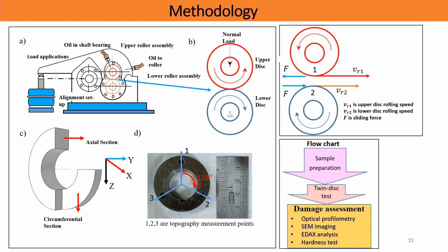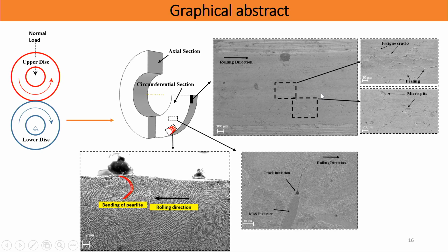So this is the figure of the tribometer. There are 2 rollers here, just like in the Abaqus model. There is a pneumatic kind of a piston here which is pushing it down to different forces, and we cut this and measure the surface at 3 points and the subsurface also along these planes. And as I said, there are different surface velocities. So we find out the slide to roll ratio as I told you.